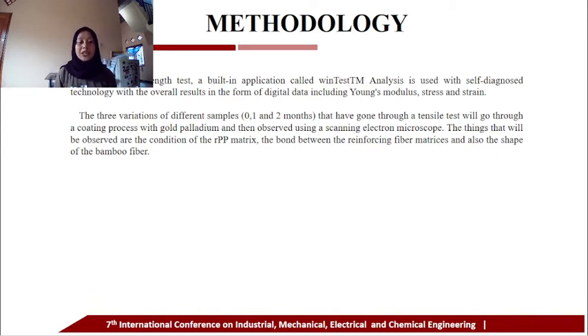In the tensile strength test, a built-in application called WinTest analysis is used with self-diagnose technology, with the overall result in the form of digital data including Young's modulus, stress, and strain. The 3 variations of different samples, which are 0, 1, and 2 months samples that have gone through a tensile test, will go through a coating process with gold palladium and then be observed using a scanning electron microscope or SEM. The things that will be observed are the condition of the recycled polypropylene matrix, the bond between the reinforcing fiber matrix, and also the shape of the bamboo fiber after exposure.